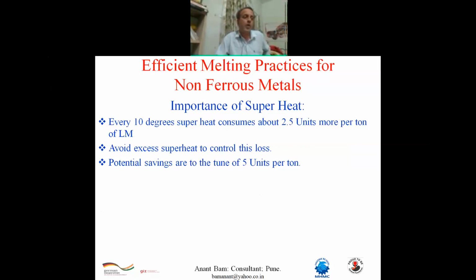How can one control the superheat or optimize the superheat? That is by process control. One can go for a warmer mold. One can reduce the travel distance, the travel time from crucible to the mold. One can use a preheated transfer ladle or transfer metal pouring spoons. By such means, we can reduce the superheat. And the saving potential is to the tune of 5 units per ton.